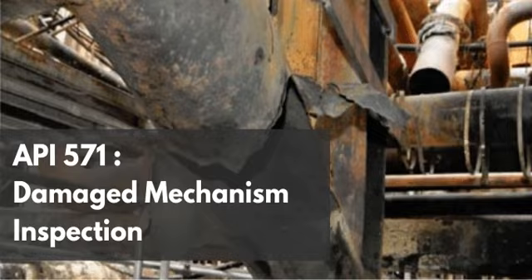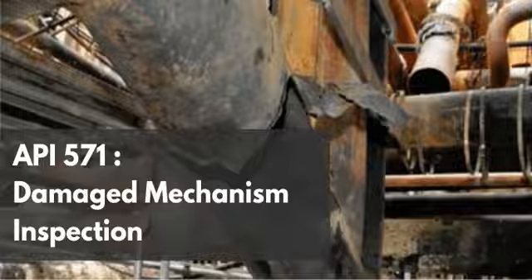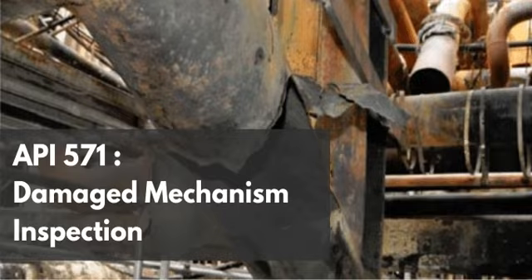As we established, the residual stress is a result of the atomic lattice being locked in a state of high tension. To relieve that tension, you have to give the atoms enough thermal energy to increase their mobility. At 1175 degrees Fahrenheit, the yield strength of the carbon steel drops significantly. So the material enters a state where localized microscopic plastic flow known as creep can occur.